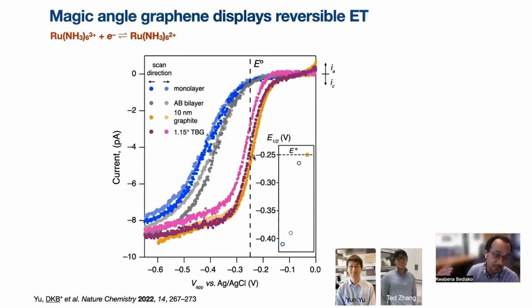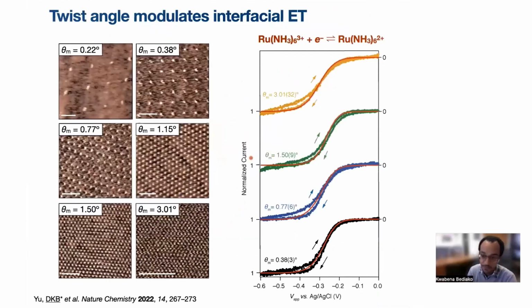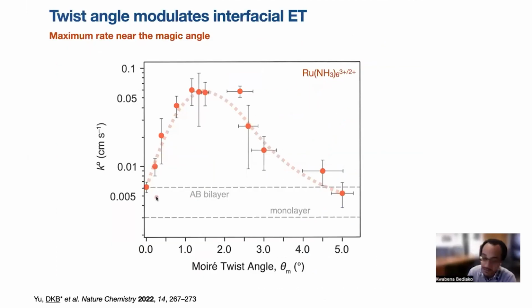So we can go ahead and make samples at different twist angles. Again, here are the STM images, just showing the variation in the Moiré superlattice periodicity. We can measure the electrochemistry of these samples, and we can plot the rate constant on this semi-logarithmic plot as a function of the twist angle, and we see that there's a very strong modulation in the electrochemical rate constant as a function of twist. So this was for the ruthenium 3+/2+ couple.